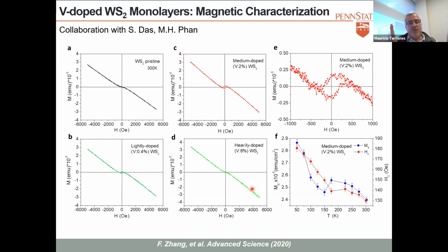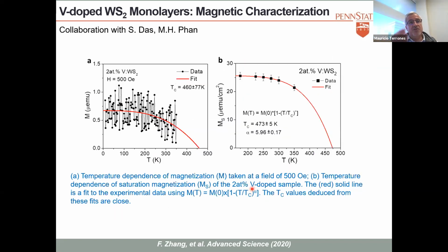So you are doping with vanadium atoms, and then when you are applying a magnetic field, you are magnetizing, and the spins can go in one direction or the other direction if they are far away. As you start to bring them together, they interact with each other, and then you have an antiferromagnetic sort of pair. And that's what happens when you have so many vanadiums close together. They cancel each other because you have these antiferromagnetic systems. When they are far away, you can still see the ferromagnetic signal. So that was very interesting because you can see this as a function of the amount of vanadium that you are incorporating.